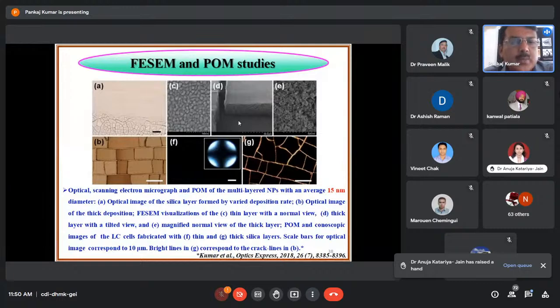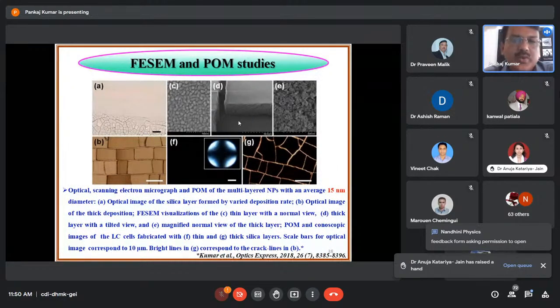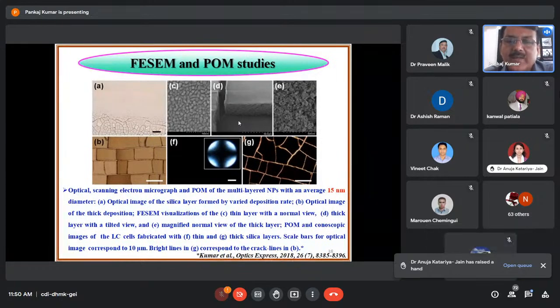POM and conoscopic images of the liquid crystal cells fabricated with thin and thick silica layers are given by figure F and figure G. In figure F, you can see the perfectly dark state and a very good conoscopic image, as well as in figure G, where the thick silica layers are used. Scale bars for optical images correspond to 10 micrometers.